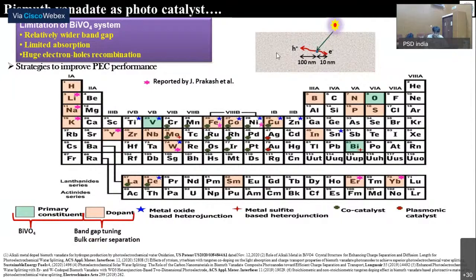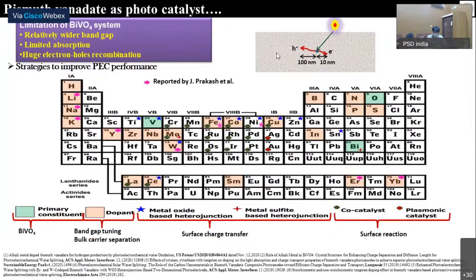So with the doping, we can do band gap tuning as well as enhance the bulk charge carrier separation. The second strategy we can adopt is to put a metal oxide or metal sulfide based heterojunction on the back and front of the bismuth vanadate. Even if the thickness of bismuth vanadate is less, by putting this heterojunction, we can improve the surface charge transfer. And whatever charges are reaching the surface, they efficiently do water oxidation. For that, we can use several co-catalysts or plasmonic catalysts. So in today's presentation, I will be only talking about the doping part, especially sodium and potassium alkali metals.